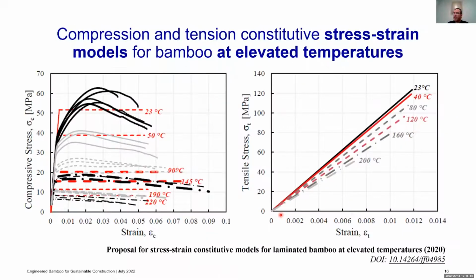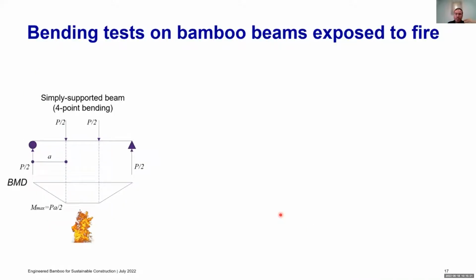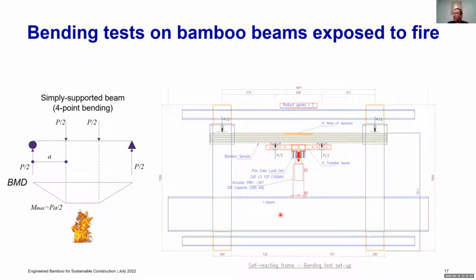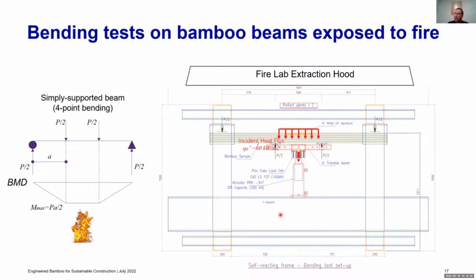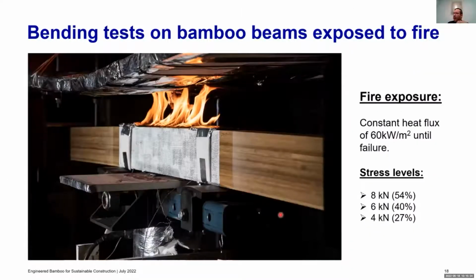So with that information, we built some constitutive stress-strain models. And with those models, and after understanding the properties of the material, we moved to full-scale testing. We conducted a 4-point bending test because that was the easiest test to make. We defined one thermal exposure, and then we applied 3 different stress levels: 54% of the failure load, 40% of the failure load, and 27% of the failure load.